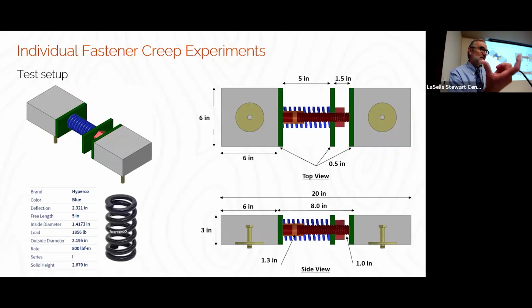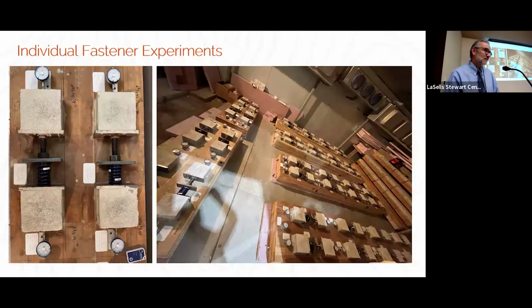So if you preload them in compression, they're going to sustain that force with very little force drop off, even if you have some deformation. And every single spring that we use, and I'll show you a picture, this is what it looks like in the actual laboratory. It's inside an environmental chamber to try to damp out some of the temperature and relative humidity changes that take place. It's kind of crazy looking, but every single one of these includes two fasteners, in opposition to one another.